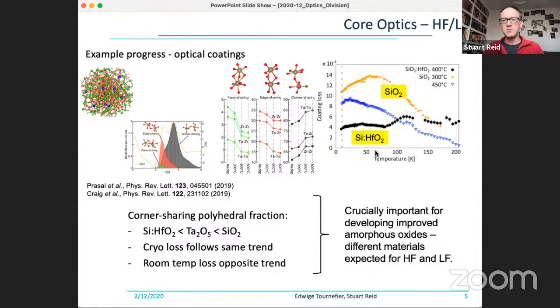And then if you look at other papers, this is an example plot from Kieran Craig's paper last year as well. We can see that certain materials like fused silica, which we know as a coating material, I haven't drawn the plot there, but at 300 Kelvin, this comes down to at least 5 times 10 to the minus 5, so very low mechanical loss. And so as a room temperature material, silica looks really attractive, but as we go to cryogenic temperatures, we can see that actually this is a high loss material. And then we look at other materials like this silica hafnia alloy. Low temperature, this looks quite nice, but as we go up towards room temperature, it then becomes the highest dissipation material of the ones studied here.